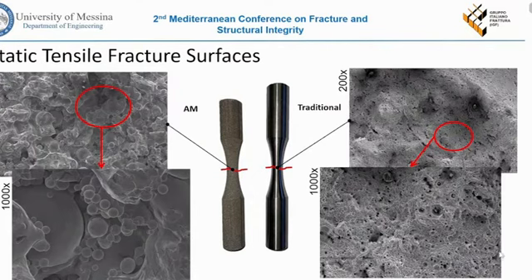By analyzing the fracture surface with the SEM, we can see how the additive manufactured material exhibits a brittle fracture surface under static tensile load and several macro defects such as unmelted powder. On the other hand, the traditional material exhibits a very ductile fracture surface with small defects compared to the additive manufactured one.